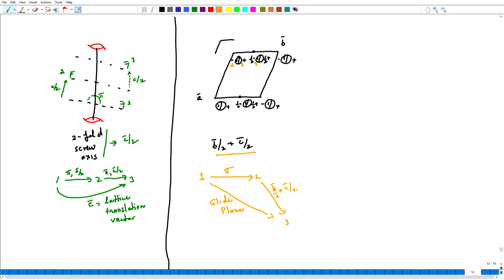So, that glide plane, how do I represent this? Well, I represent it like this, and it is 1/4 above. So, I also have to write down 1/4 to indicate that this particular glide plane that I am talking about is 1/4 along the C axis above the AB plane.